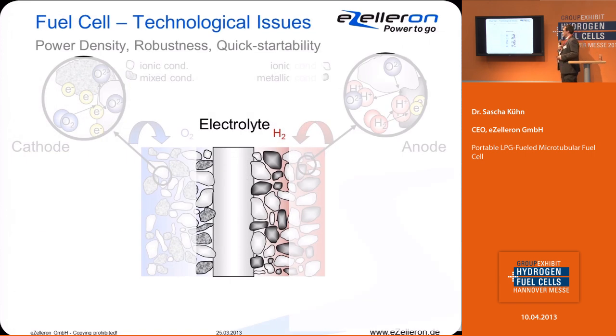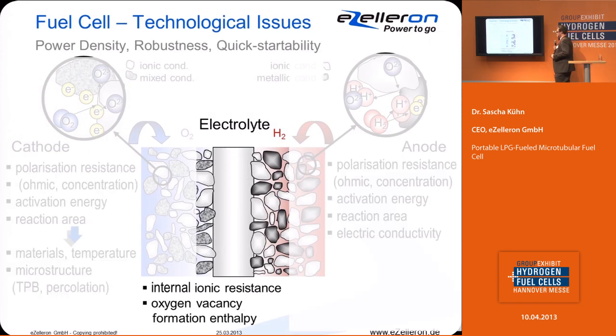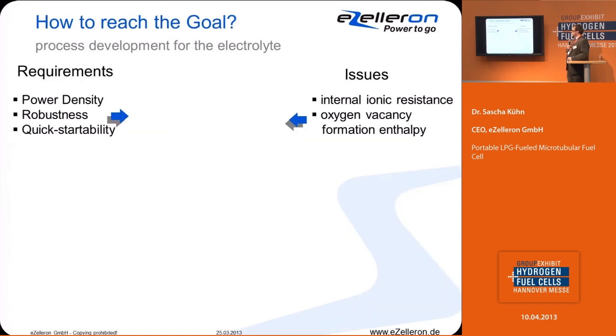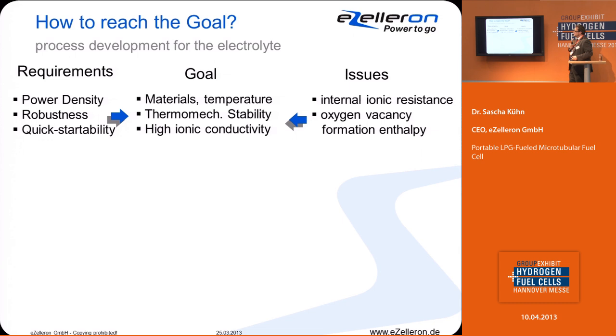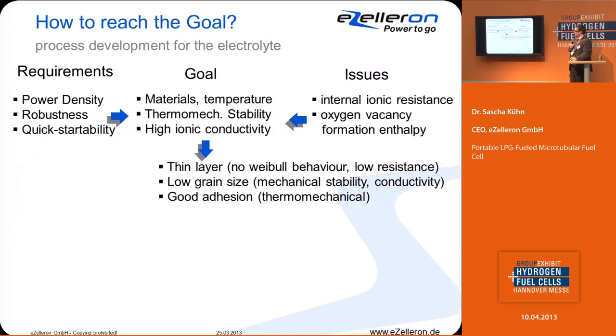So the next step is how to manufacture the electrolyte, and there are a lot of things important for the electrolyte, mainly the internal ionic resistance and the oxygen vacancy formation enthalpy. And always you have to keep in mind that we want to build a system that has a very high power density, robustness against thermal shocks, and quick startability. And during that we want to overcome these issues. That means we have to care about all the materials, the temperatures, the thermomechanical stability of the whole system, and still we have to improve the ionic conductivity.